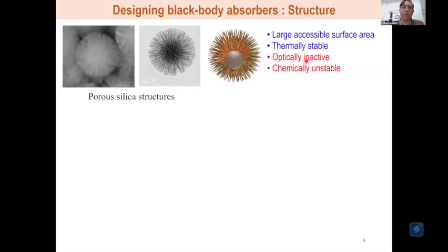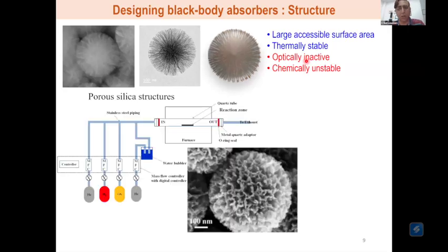So now what we do is we take this material, want to leverage the morphological aspect of this, and therefore we coat this with carbon. We do this through a process of chemical vapor deposition, where you send in acetylene at high temperature. Acetylene, by controlling the conditions, is the carbon source, and you can start depositing carbon all along the silica walls. And once you do that, you can conveniently remove the silica, because SiO2, you put it in an alkaline medium, sodium hydroxide or potassium hydroxide, it dissolves by forming silicates, sodium silicates or potassium silicates, and those are completely soluble in water.